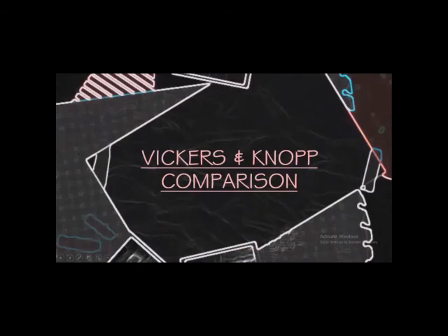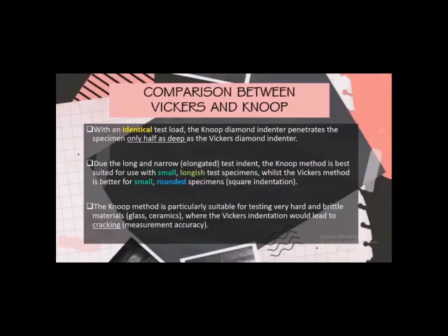Hello, this is Ify. Now I want to explain about the comparison between the Knoop and Vickers methods. Basically, the Knoop method represents an alternative to the Vickers method. And here is the comparison between both of them. The first is with an identical test load, the Knoop diamond indenter penetrates the specimen only half as deep as the Vickers diamond indenter. Due to this shallow indentation depth, the Knoop method is more suitable for testing very thin layers, for example aluminum foil. Second, due to the long and narrow test indent, the Knoop method is best suited for small, longish specimens, while the Vickers method is better for small, rounded specimens.